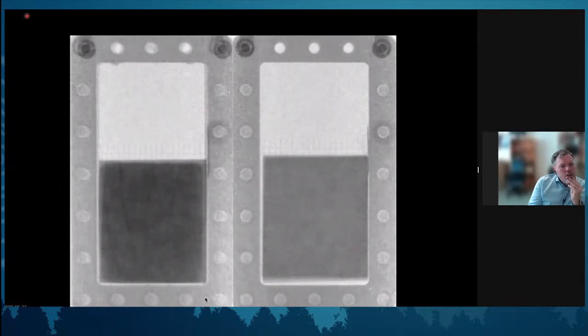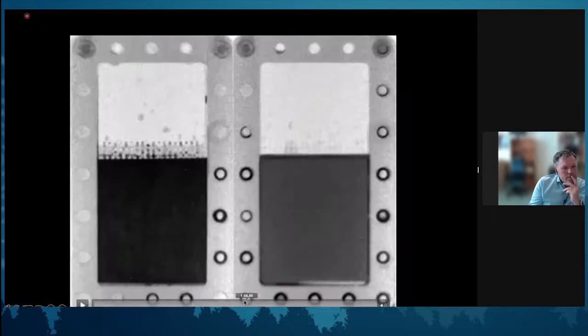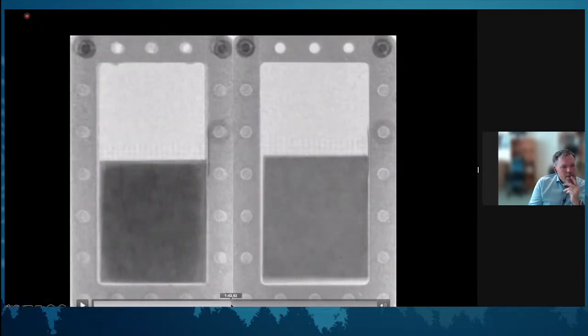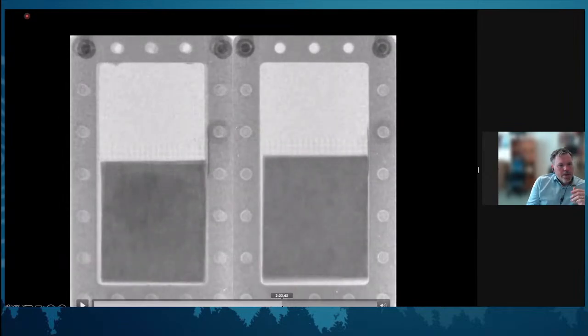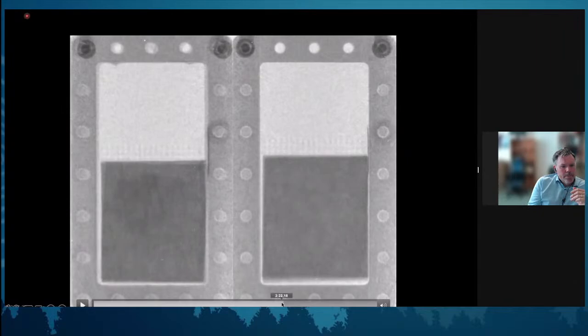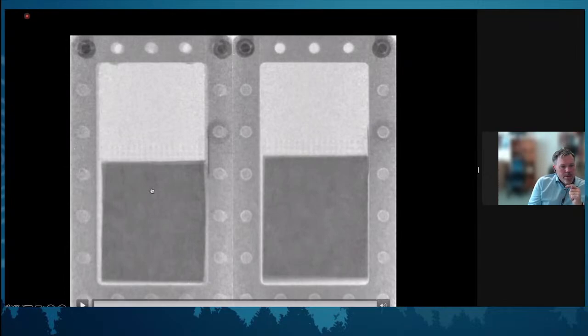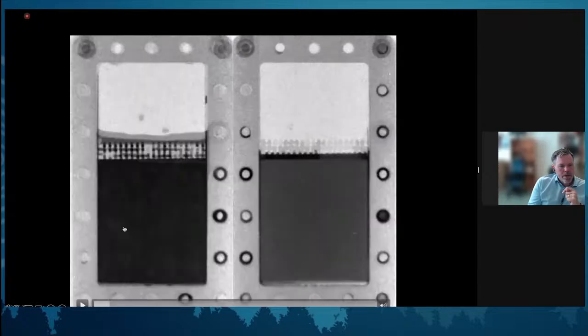And it takes a much longer time to dry for the left one than the right one. Sorry. So what we see is that it dries, and we get a spot in the center as well here. And when we reach the total, all water is taken away, we can see that the amount of cellulose is actually the same. So the only thing that differed when we started was that we had about twice the amount of water in the left one.